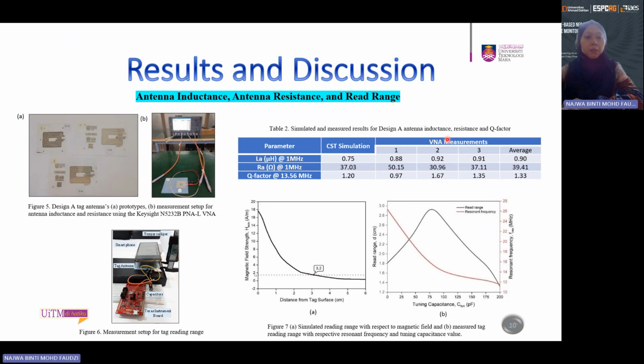From the result here, we can see that the measured value on average agrees well with the simulated value, and these findings demonstrate that the graphene-based conductive material is well printed and compatible with the flexible PET substrate. We can see here the inductance of the tag antenna is 0.9, and from the simulation is 0.75, which is almost similar to each other.